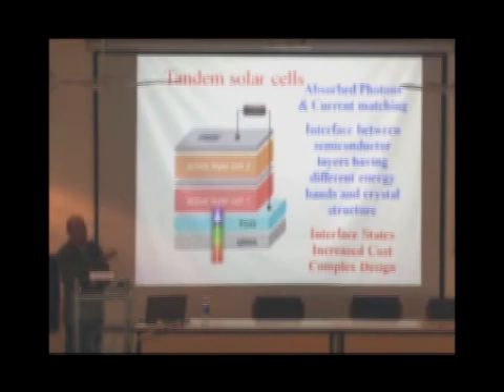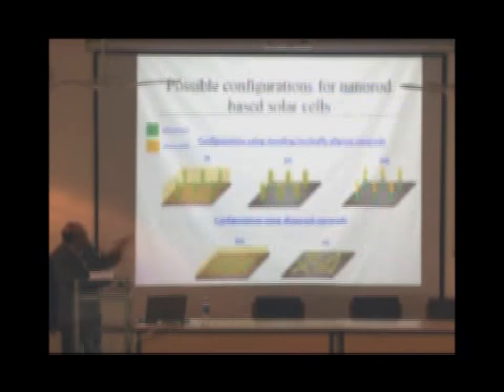The other problem is the interface. When you're forming an interface between different semiconductor materials, there are defects at the interface, there are structural inhomogeneities, the lattice constants of the two semiconductors will be different, that will result in a large number of dangling bonds and so on, and the design becomes complicated. So what is proposed is that it's possible to use nanorods of semiconductors, and you can change the diameter of the nanorod, and you can change its band gap.